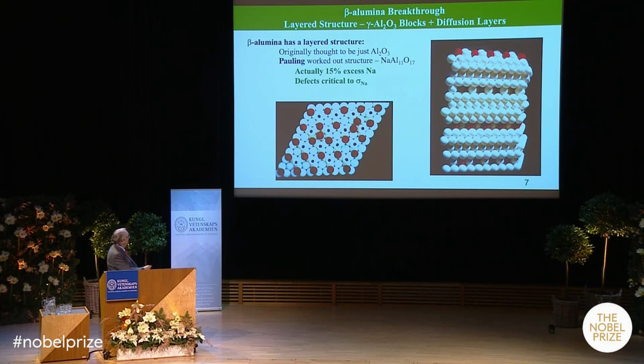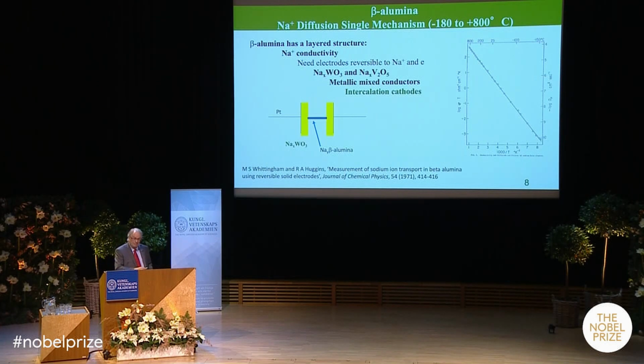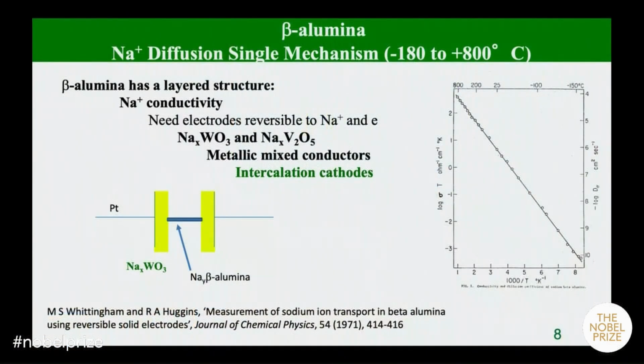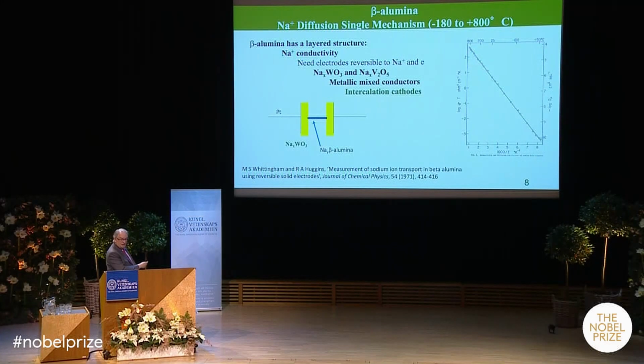But then came the real challenge. How do we measure how fast these ions move? You can't just put regular electrodes on because they're moving too fast. So we went back to our tungsten bronzes. So here we have the same tungsten bronzes, whether the tungsten or vanadium ones. These are mixed metallic conductors. So if you want to measure ionic conductivity, you've got to have electrodes that move both electrons and ions. So we built up a simple cell here, tungsten oxide electrodes, then in the middle here, single crystals of this beta alumina. And then we could measure the conductivity over this range, about -180 to 800 degrees centigrade.